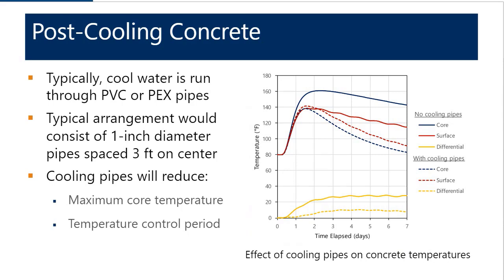So depending upon the type of project that you may have, you may be able to install cooling pipes and reduce the time period in which your temperature control period is in play. And so here we can see a graph here on the right, and what you'll notice is a scenario where no cooling pipes are installed, and you can see that with the solid lines, and so the core temperature is noted in blue. And then you also see a scenario with cooling pipes installed, and that is denoted with the dashed lines.